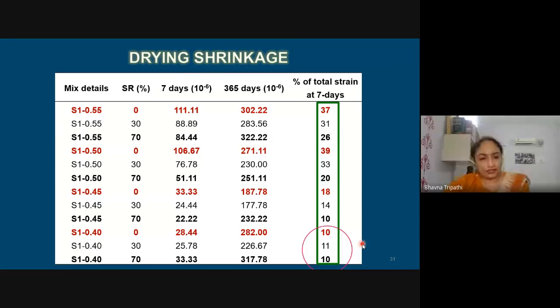The reason may be that because of lower water cement ratio, the quality of concrete is better, the porosity is less, and the mix is dense, and therefore shrinkage, which is directly affected by the pore water, is less. When you don't have much pore water inside, the shrinkage will also be less.